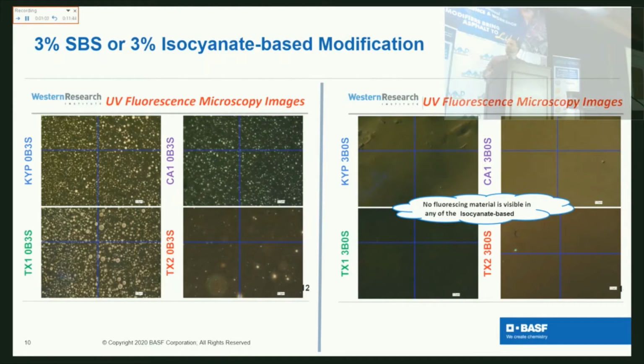And as you can see, this really just proves out my previous slide in saying that once it's chemically reacted, you can't see it anymore. It is gone within the structure of the asphalt. We have run some FTIR studies and noted that you can react the material so it's no longer detectable on an FTIR.